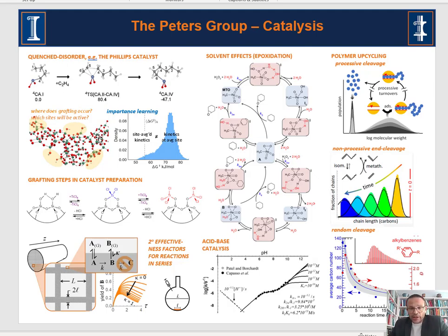So if you look at the entire panoply of olefin transformations, there's polymerization, there's epoxidation, there's metathesis. A lot of those catalysts are made this way. They're single metal atoms or a single metal atom precursor grafted to an amorphous support, and now all of those metals are sitting in a unique environment. And so it kind of deviates from the textbook description of catalysis, and yet industry is really using these. So we dove in and decided, we develop computational methods, so this is a perfect area for us, and we should try to figure out how to do this.